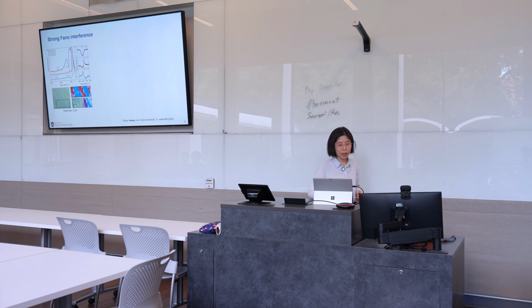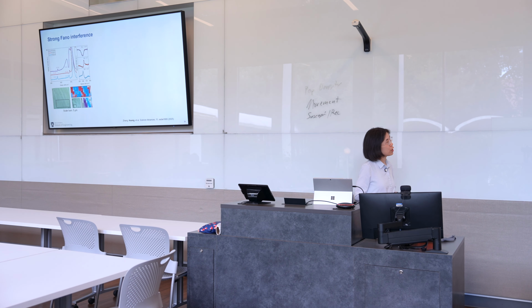For example, if you look at the optical image of this 2D silver surface, you can see these striped structures. These are actually due to the different terraces of silicon carbide. We know the silicon carbide, in our case, is 6H silicon carbide. It can have different surface terminations, and this gives you these structures of terraces. Now, if we map this structure and the phonon patterns, we realize the FLO 2,4 and FLO 2,5 actually show up alternately. So apparently, these phonon patterns are dependent on the surface termination.